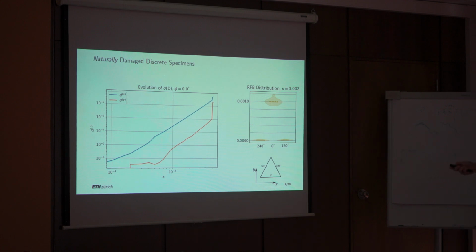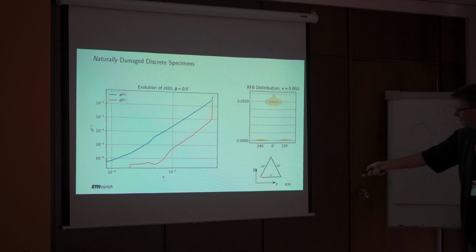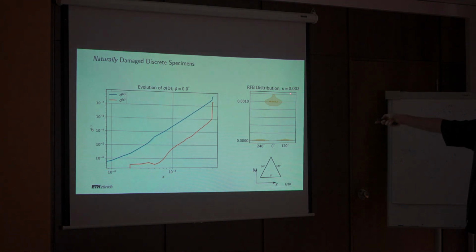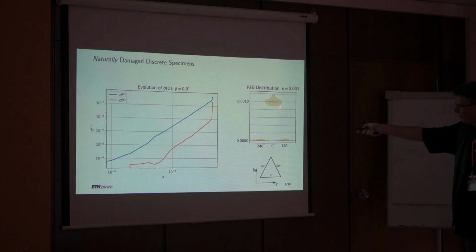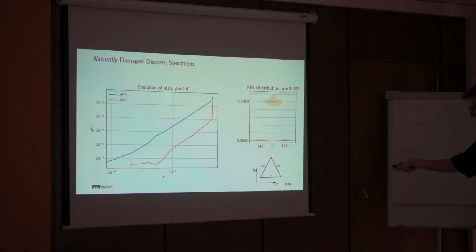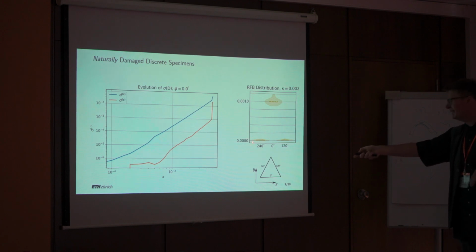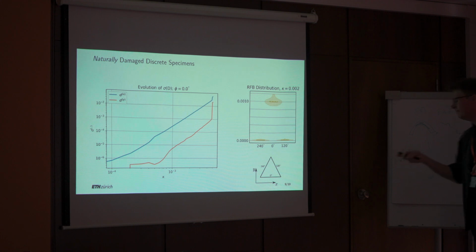And here you see a wireline plot. This basically tells you which beams have failed. You see, we have 3 different kinds of beam: horizontal and 2 inclined beams. And here you see that the majority, when we pull along the x direction, excuse me, I forgot to mention this. This here shows the state at the strain of 0.002. And you see that the majority of beams that have failed are horizontal beams, which is basically what I have told you, and just a very tiny fraction of the inclined beams have failed.